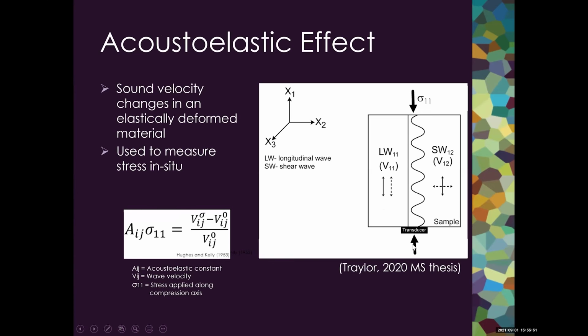We have our loading direction in the vertical direction, and we have our waves propagating along this direction. This dependency of wave velocities on the stress state is known as the acoustoelastic effect. And this technique is used in metallurgy to measure the stress in situ at ambient to very low pressures. Without going into too much of the theory, it's been shown that the change in wave velocity is proportional to the uniaxial stress state through these proportionality constants, Aij, these acoustoelastic constants.